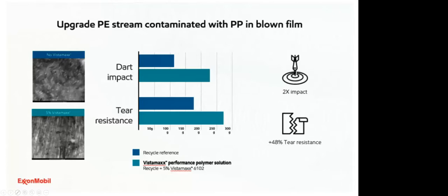What is very interesting to see here is that the impact strength of the film improves twice with the addition of only 5% of Vistamaxx, and you can improve almost 50% the tear resistance of the film, just by improving the compatibilization of the two different polymers.